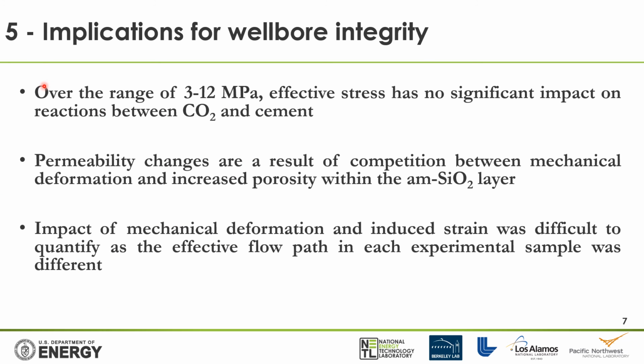To conclude, over the range of 3 to 12 MPa, effective stress had no significant impact on the reaction between CO2 and cement. The permeability changes were the result of a competition between the mechanical deformation that led to a decrease of permeability and the increase of porosity within the amorphous silica layer, which leads to an increase of permeability. At last, it was a little bit difficult to quantify the impact of mechanical deformation and induced strain because the effective flow path was different in each sample.